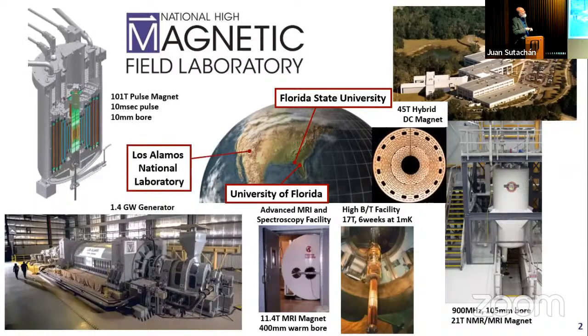And then out in Los Alamos, we have a very large installation where we pulse magnets. So we don't try to cool them with the cooling water. We turn them on and off in less than a second, 10 milliseconds in this case, so that the magnet heats up, but not so far that the whole magnet melts. Because if we ran these magnets for more than 100 milliseconds, we would make 7 tons of molten copper. And this is the highest magnetic field that's ever been generated without blowing something up.